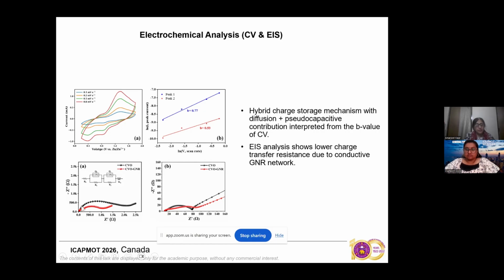Then if we take the EIS, that is the electrochemical impedance spectroscopy, we have used this model, that is two resistances with the CPE. In this case, the charge transfer resistance has a smaller value. Because the smaller the value, the better the ion transport will take place. And so in this way, the CVO GNR is much better.